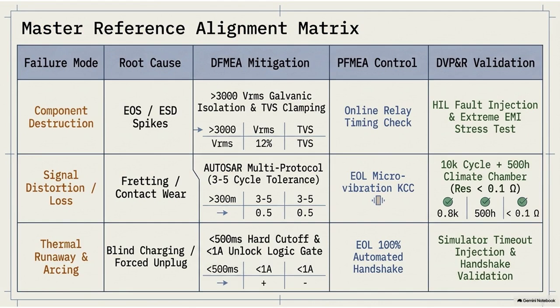10,000 insertions. If you plug your car in every single day, 365 days a year, 10,000 cycles is over 27 years of daily charging. And even after 27 years of friction, plus being baked in an 85-degree, 95% humidity sauna for weeks to force catastrophic oxidation, the electrical resistance of those pins cannot fluctuate by more than 1/10 of an ohm. When a driver plugs their car in during a blizzard in Minnesota, or during a sweltering, humid heat wave in Florida, they don't think about contact resistance or galvanic corrosion or optical isolators. They just expect it to work safely. The physical robustness required to guarantee that mundane expectation is staggering.